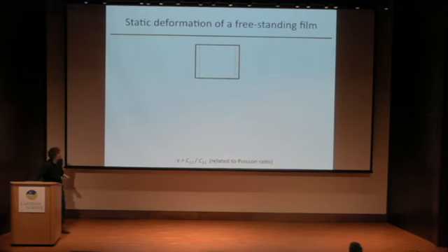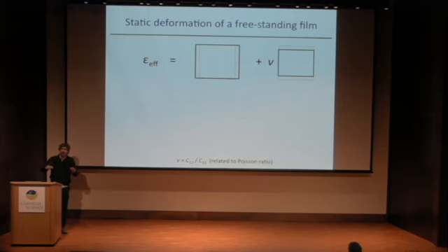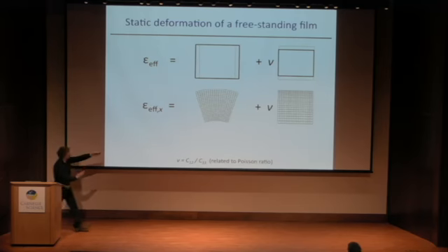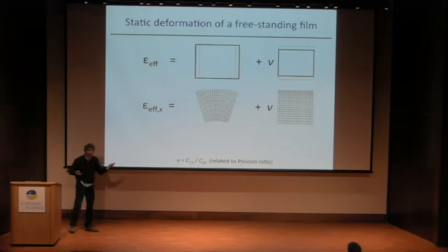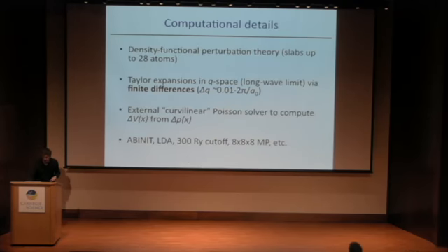There is one little detail to remember when we do strain gradients, which is that when you apply a strain gradient deformation, there is always a secondary strain gradient that appears because of the elastic equilibrium condition. For example, here, if I do this kind of deformation, I pull the surface region on one side and I compress it on the other. So because of the Poisson ratio, I will have simultaneously a longitudinal strain gradient, and the result will be the sum of the two if I relax the whole structure. Computational details, please ask me later.